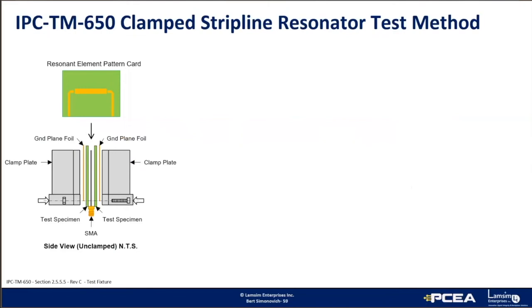One common method used by many laminate suppliers is a clamped stripline resonator test method as described by IPC TM650. It was designed to rapidly test dielectric material in a production environment. The measurements are made under stripline conditions using a resonant element pattern card made out of the same dielectric material to be tested. The card is then sandwiched between two sheets of uncladded dielectric material under test, and the whole structure is then clamped between two large plates lined with copper foil reference planes.